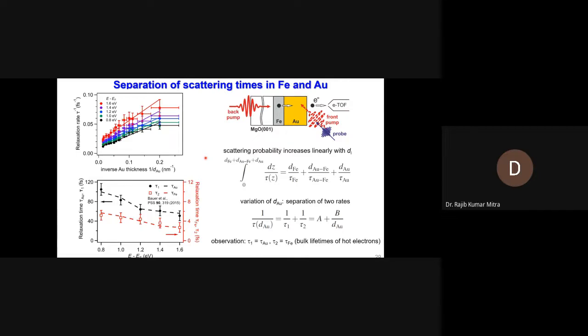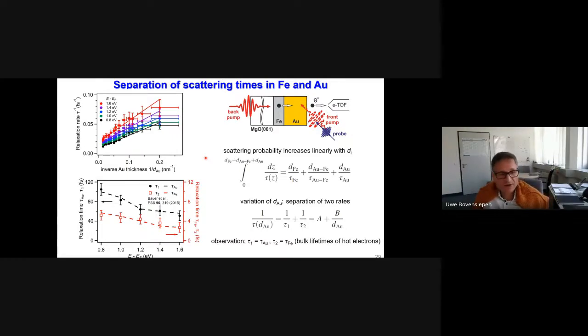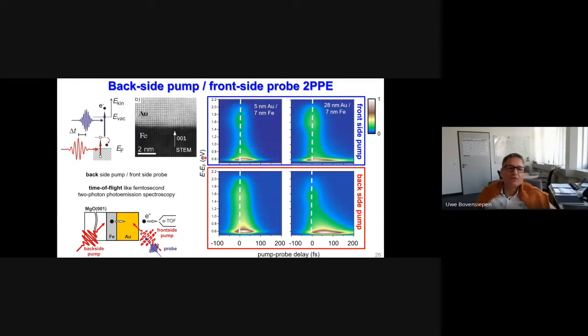Professor Bovensiepen, let me ask a brief question regarding your second part, in which you talked about the separation of scattering in iron and gold. Is it very specific to iron and gold, or could any such heterostructure work? Again, these experiments are delicate, and it's usually the work of a PhD thesis to develop this. One key idea early on was that we use iron-gold on MgO because it's an epitaxial system. The iron and the underlying MgO have more or less identical lattice constants. The gold lattice constant matches well if you in-plane orient by 45 degrees. This is why we have worked for more than a decade on these iron-gold heterostructures.